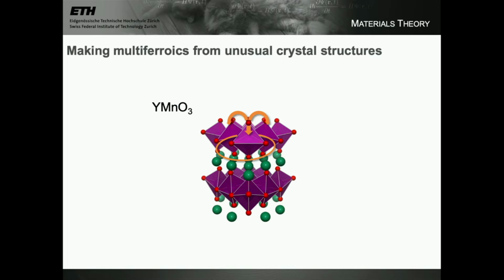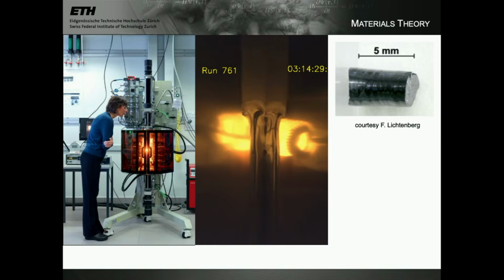And so this unusual structure leads to electric dipoles, even in spite of the fact that the manganese is magnetic. So this was a second approach. And again, these materials existed, but not in good enough quality samples to be able to reveal their multiferroic properties. And so in this case, we were able to make rather beautiful single crystals using floating zone. This is a quite large half a centimeter crystal grown by my colleague Frank Lichtenberg. And you can see, yeah, it's a very beautiful crystal. It looks black. It looks like a metal. It's actually not. It's a rather good ceramic, but it has quite a narrow band gap, and that's why it has this black color, but it's actually a very brittle ceramic material.